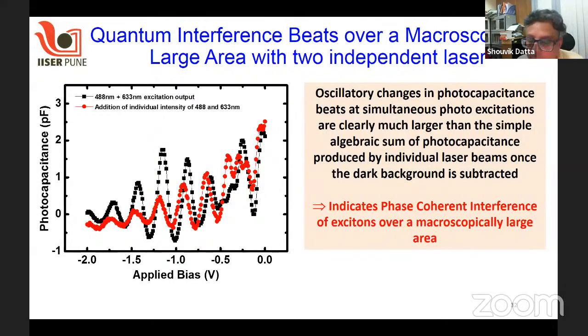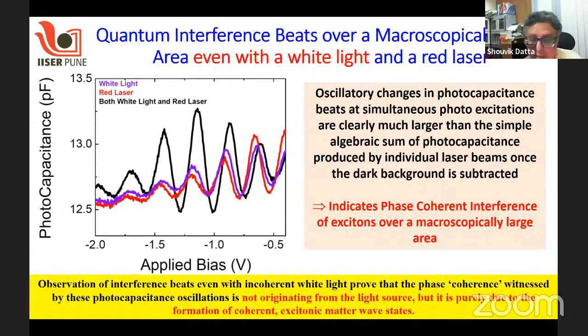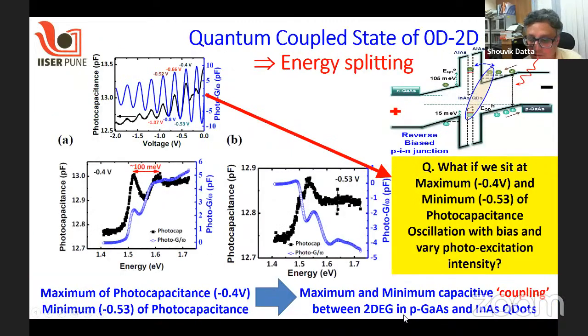Once you actually subtract the background, that's kind of indicating phase coherent interference of excitons over a macroscopically large area. People can say, well, this phase coherence may be coming from the lasers, but we have done the same experiment recently, even with white light and a laser, and white light is not a coherent light. So it clearly indicates that whatever phase coherence we are seeing, which is leading to such beat patterns, is actually being generated within the solid and not coming from the photoexcitation source.